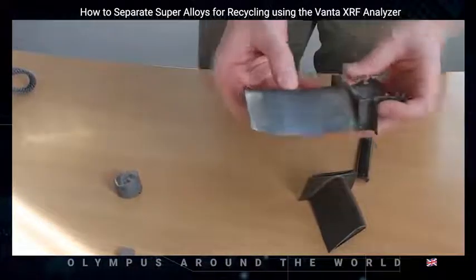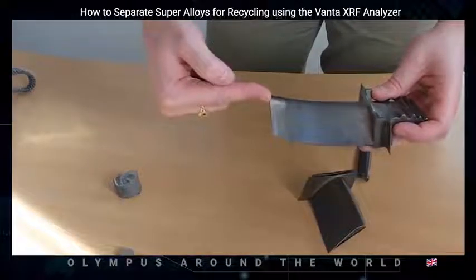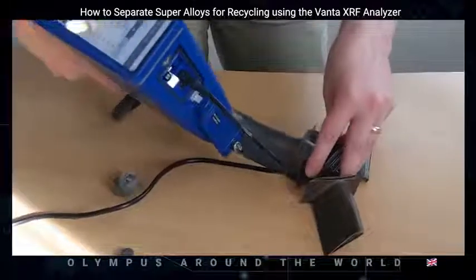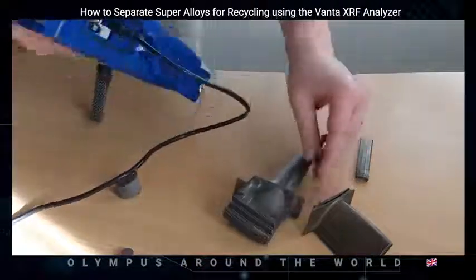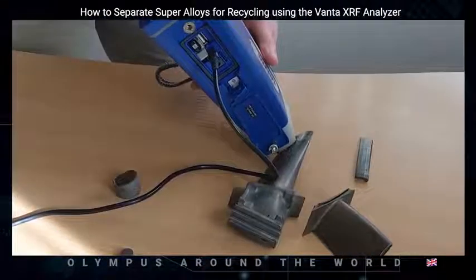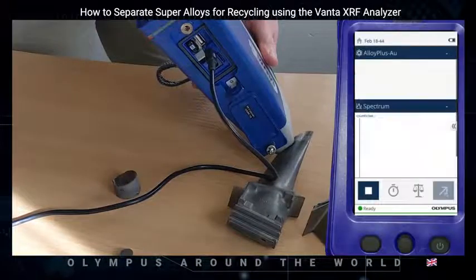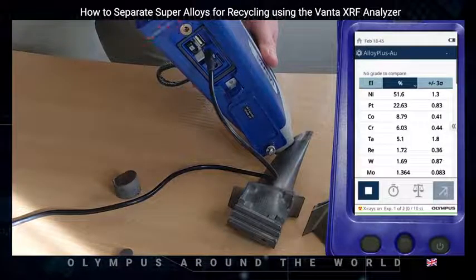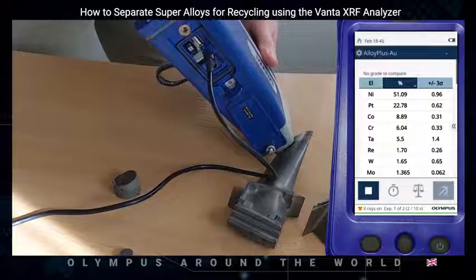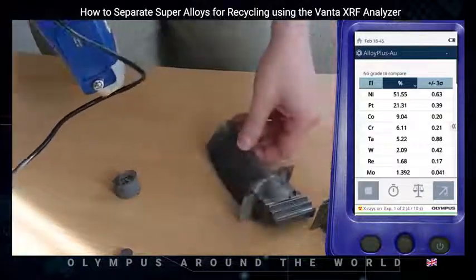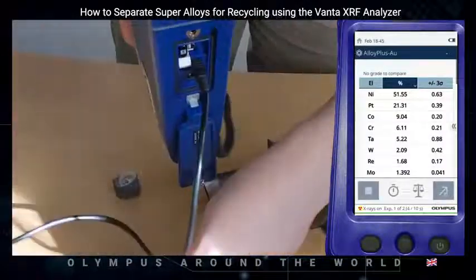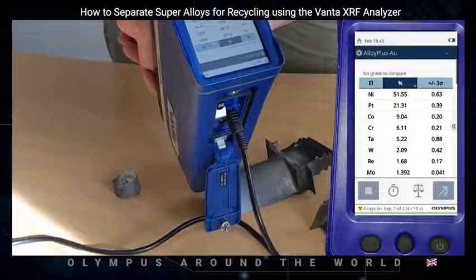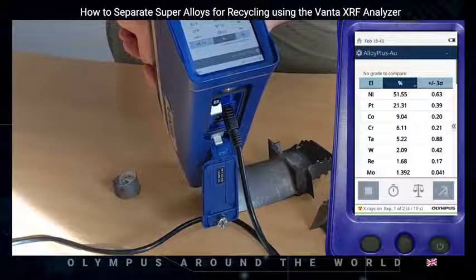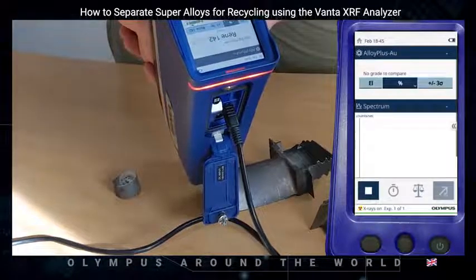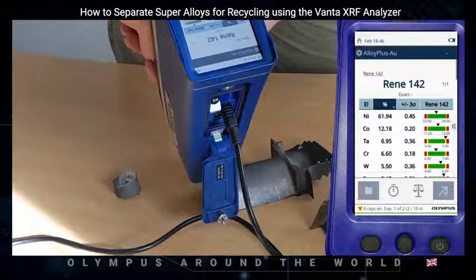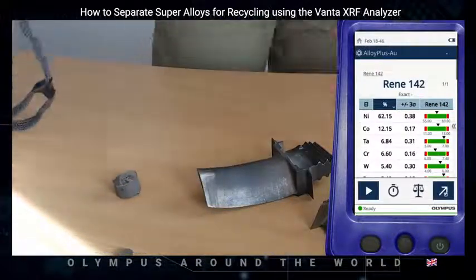As you can see on this turbine blade, the sample has been ground down at one point, so if we test an area that's not been sample prepped first, you'll notice the chemistry doesn't give us a grade match and that the platinum level is really high, and that's because this blade is platinum coated. If we test the area that's been ground off, however, you will see that we get a grade match that is an exact match for René 142.